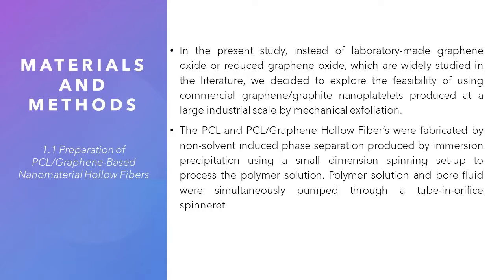Materials and methods. Preparation of PCL graphene-based nanomaterial hollow fibers. In the present study, instead of laboratory-made graphene oxide or reduced graphene oxide, which are widely studied in literature, we decided to explore the feasibility of using commercial graphene or graphite nanoplatelets produced at a large industrial scale by mechanical exfoliation. The PCL and PCL graphene hollow fibers were fabricated by non-solvent induced phase separation produced by immersion precipitation using a small dimension spinning setup to process the polymer solution.